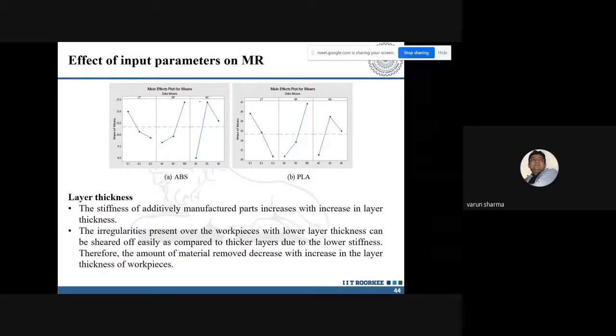Now, in the literature, what we found is that people claim that 70% is better because the more abrasive particles, the more the material removal. That may differ from case to case, and from the material that we are going to finish. Now, similar kinds of trends have been achieved for the ABS as well as for the PLA kind of material.